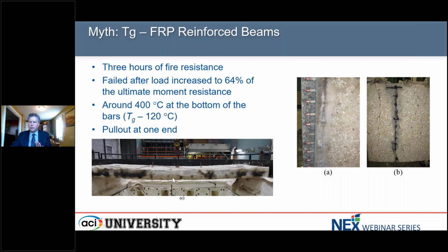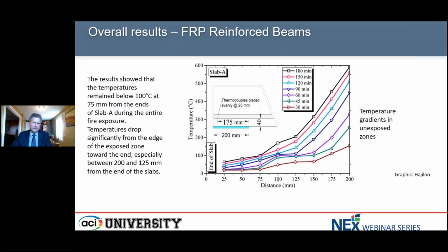So we still had adequate strength of the bars at the center, but what it did affect was the bond. And you'll see at the end here, we did get some pullout, and that was a result of the high temperature. That pullout was the fact that we started to lose the bond strength. But just a little bit of overlap, and this overlap here is only about 8 inches that we had protected from the fire at the end. With that little bit of anchorage to protect the bond strength, we were able to have a successful fire test. And these are some results showing what the temperatures are. These are the temperatures at the end of the slab where it is protected.